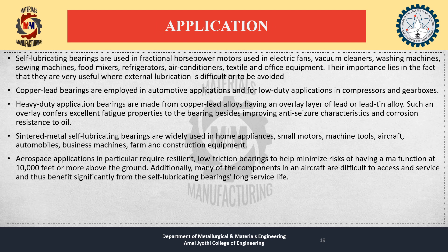Applications of self-lubricating bearings: They are used in fractional horsepower motors in electric fans, vacuum cleaners, washing machines, refrigerators, air conditioners, etc. Copper-lead bearings are employed in automotive applications. Heavy duty application bearings are made from copper-lead alloy with an overlay layer of lead or lead-tin alloy, which confers excellent fatigue properties and improves anti-seizure characteristics and corrosion resistance. Sintered metal self-lubricating bearings are widely used in home appliances. Aerospace applications in particular require resilient, low-friction bearings to minimize the risk of malfunction at 10,000 feet or more above ground. Many components in aircraft are difficult to access and service, and thus benefit significantly from the long service life of self-lubricating bearings.